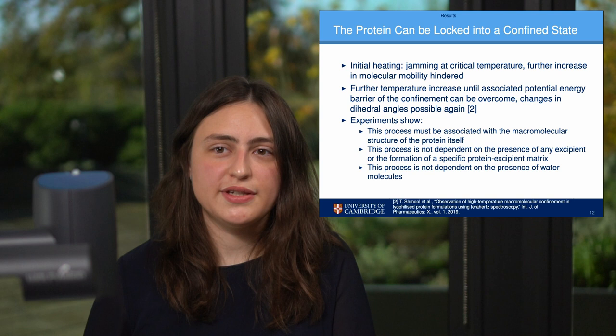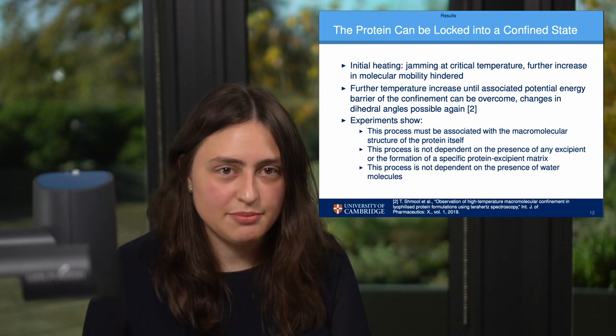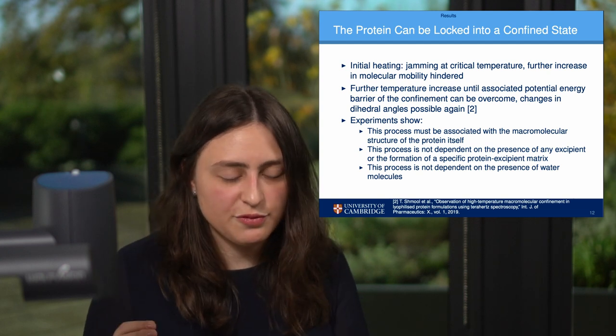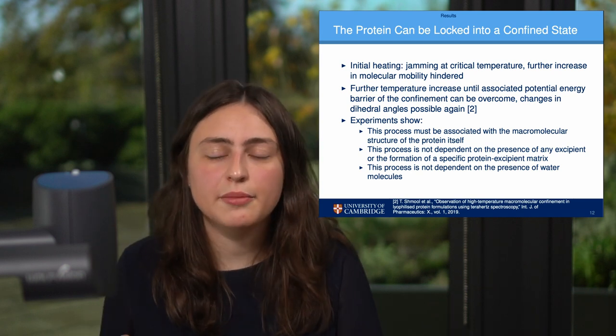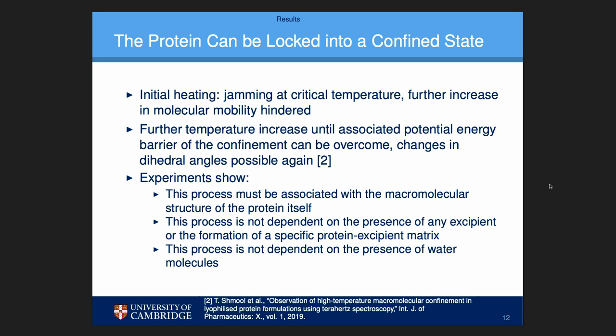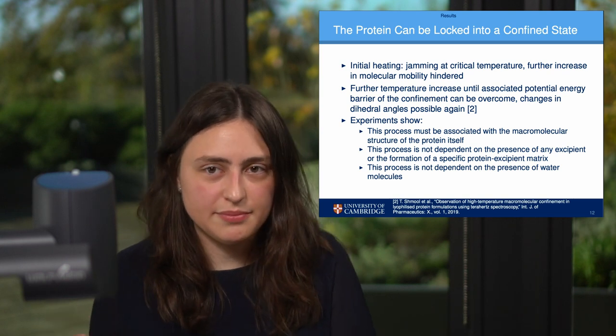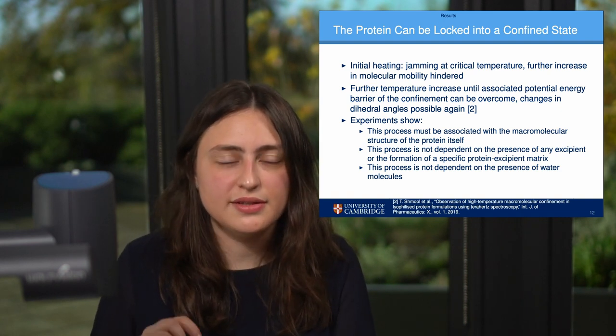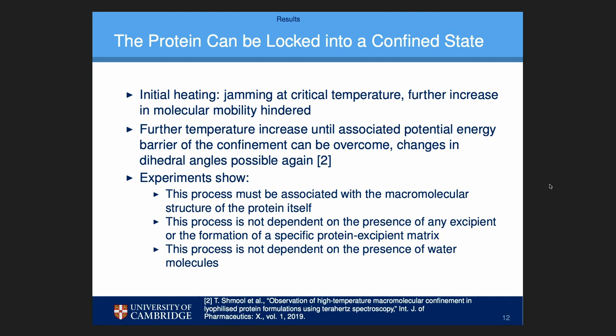We do see the jamming and the plateau in samples containing sucrose, but we also see it in samples containing only the antibody. So we can see that this jamming depends only on the antibody and not on the sucrose. We can also say that it doesn't depend on the presence of water, because we control the experiments so well that there is almost no water in the samples at all. The jamming really depends on the protein itself.